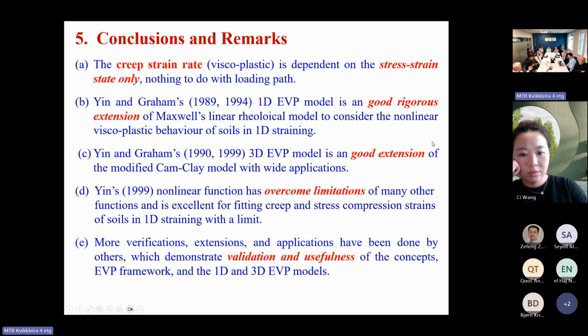My three-dimensional model is a good extension of the modified Cam-clay model. Cam-clay cannot consider the viscosity of the soils, but my model can. In my model, when the viscosity parameter becomes 0, my model automatically reduces to the modified Cam-clay model. It's consistent, okay? And I also suggest a very simple nonlinear function to fit some good data, overcoming limitations of some functions. Existing functions give you wrong results at large stress for longer times. Some errors. I can overcome those limitations.